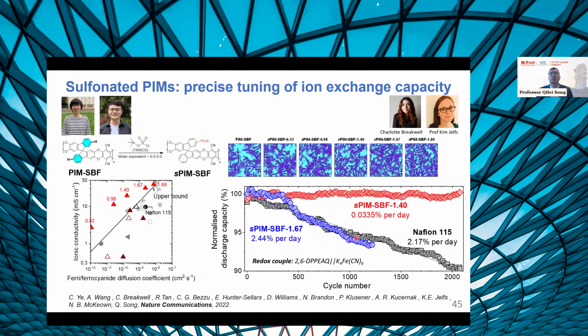Another work we did was to develop the sulfonated polymers. Again, we were able to perform the sulfonation of this traditional PIM SBF, a classic PIM polymer. By tuning the ion exchange capacity and the sulfonation degree, we were able to get higher ion conductivity and also reasonable selectivity. You can see that this new sulfonated PIM membrane gives much better selectivity because the membranes do not swell too much.